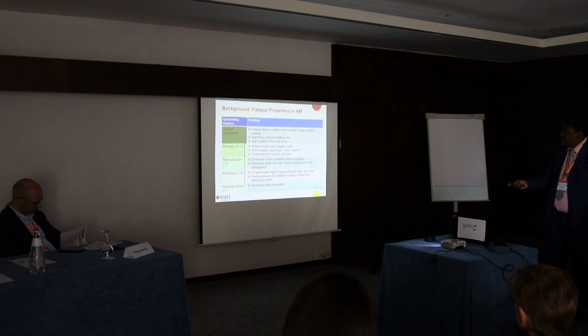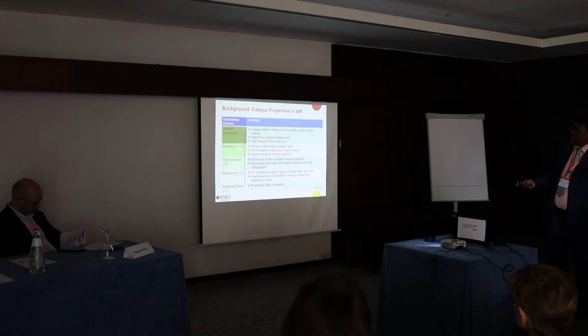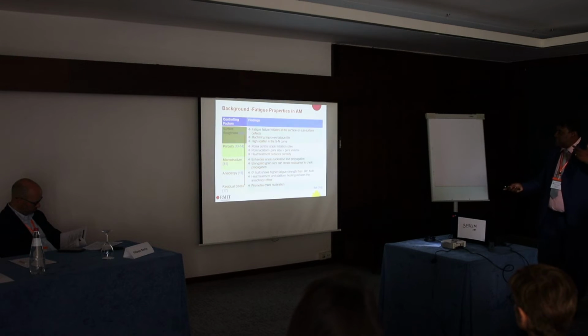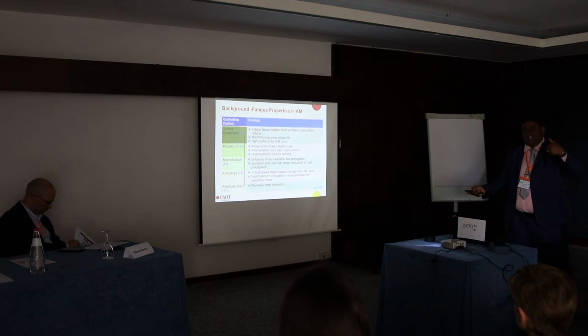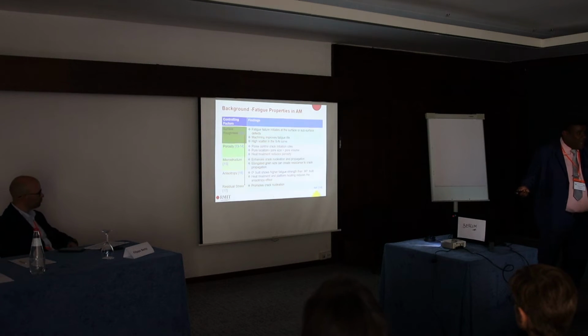Surface roughness, of course, because fatigue failure initiates at surface or subsurface defects. Machining can improve fatigue life. We can see high scatter in the S-N curve. Porosity controls where the crack initiates, and again within the porosity, the location of the pore has more influence than the pore size and the pore volume. So location, subsurface or within the bulk, will play a deeper role.